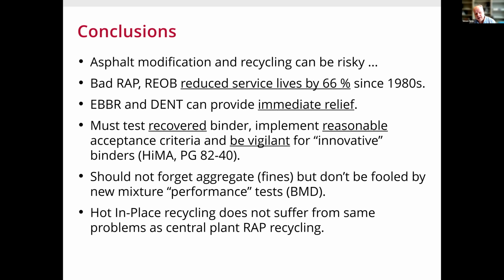The extended BBR and the dent, they can provide immediate relief, but you must test recovered binder and use reasonable acceptance criteria. You must also be vigilant for innovative binders such as these 82-40 grades, these highly modified binders. They can pass all the extended BBR, the dent test, but they don't perform well in service. And Hot in-place recycling does not suffer from that issue.